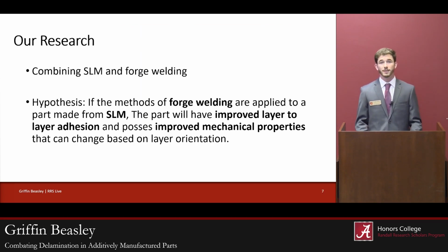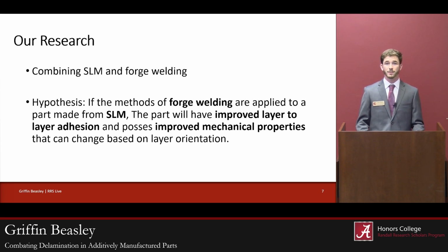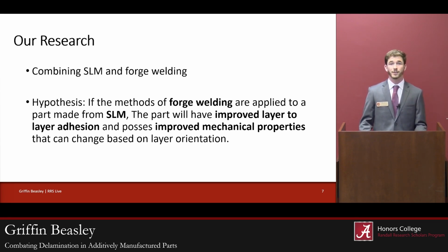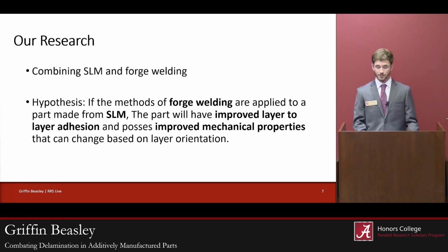Our research seeks to prevent delamination and therefore open additively manufactured parts to more applications. We intend to do this by combining the selective laser melting process with a process known as forge welding. And our exact hypothesis is that if the methods of forge welding are applied to an additively manufactured part made from SLM specifically, then the part will have improved layer-to-layer adhesion and improved mechanical properties that will also change based on the ways that the layers are oriented. Now, this raises an important question.